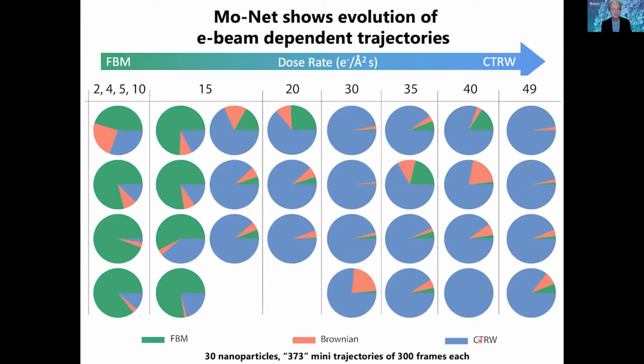And you can see here some results from that. These are for 30 particles, 373 trajectories of 300 frames each. This is a lot. In the past, this would have been very, very difficult for a human being to do, but this is done relatively straightforwardly with this instrument. And what you can see, I think, reasonably clearly is that the probability that these are Brownian motions is actually fairly low at all dose rates. But at very low dose rates, it appears that we have a fractional Brownian motion, and at high dose rates, it looks like we have a continuous time random walk kind of motion.